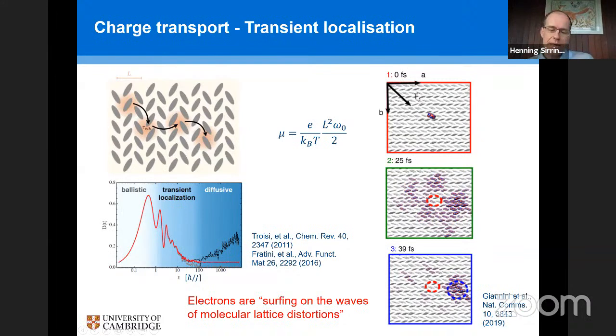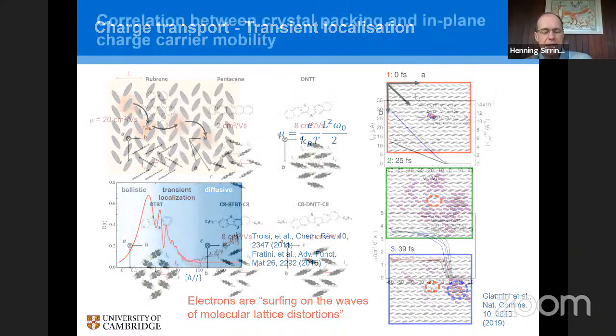So you can express the mobility in this form here. The mobility depends on two key quantities. One is the so-called delocalization length L, which is essentially the characteristic length scale over which the wave function is able to delocalize at a particular moment in time. And omega naught here is the vibrational frequency. So essentially, this is a diffusive process where every time step is determined by the characteristic vibrational frequency. Every time step, the wave function hops by a length scale L. And that is how we understand carrier mobilities in these systems.